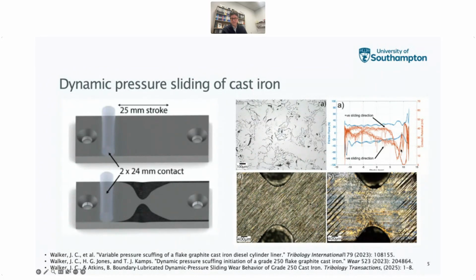You start to see asymmetric behavior depending on which way the ring or the contact is moving, and this is a squeeze film effect as we've determined, because if you put the constriction in the middle there, you get a symmetrical behavior. So this is where you get a change in velocity in the vertical direction as you're approaching the end of the stroke rather than commencing after the reversal position.